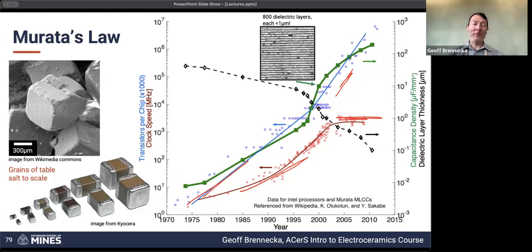Nobody ever talked about the fact that the multi-layer ceramic capacitor industry was keeping up with this, and in some cases even exceeding it over this entire range. So this is Moore's Law applied to the silicon semiconductor integrated circuit industry, and the multi-layer ceramic capacitor industry kept right up with them in terms of the number of layers per capacitor, the capacitance density per volume, all of that. Just unbelievable scaling that went right along with it. Up here at the top, I've got an example of 800 dielectric layers, each less than a micron, and this was in 2000. And that process has continued since then.